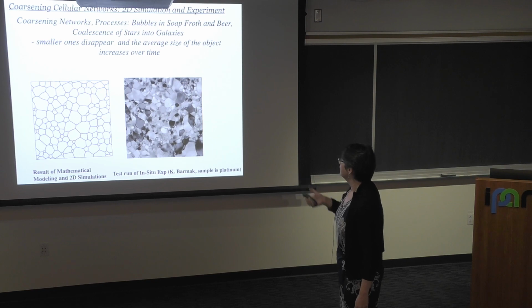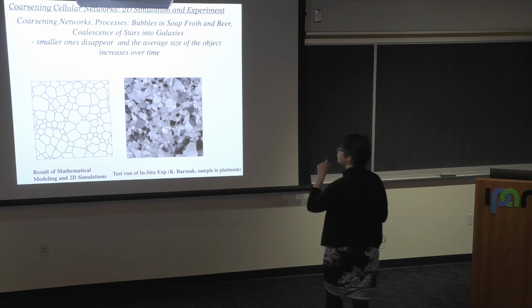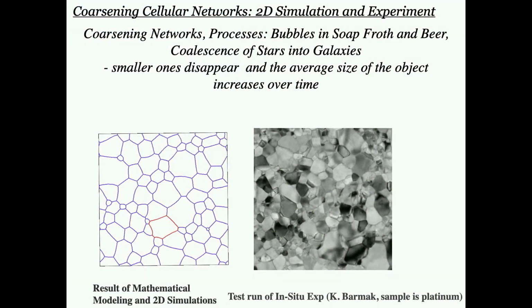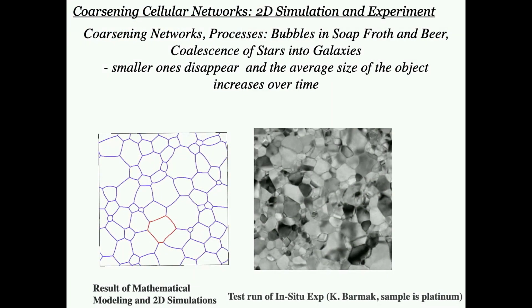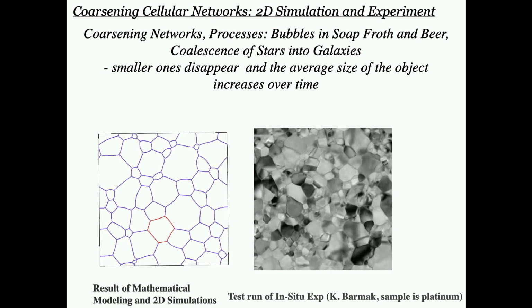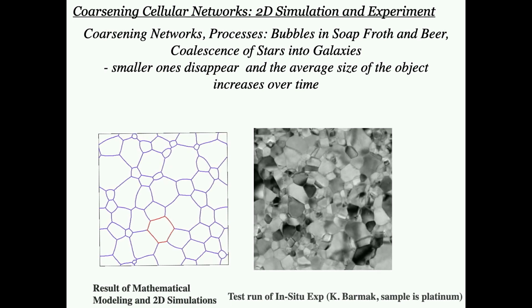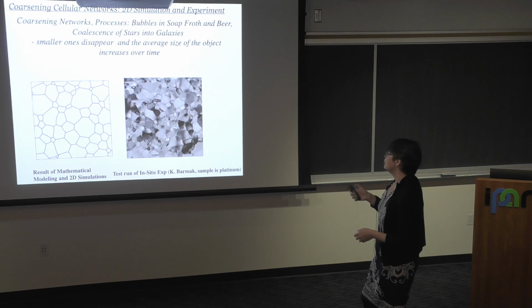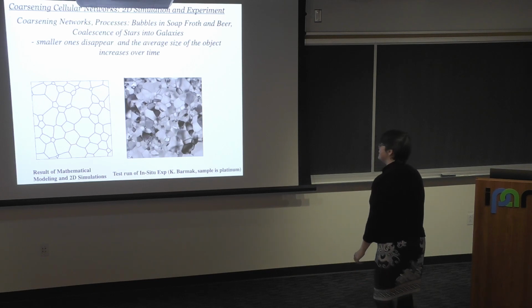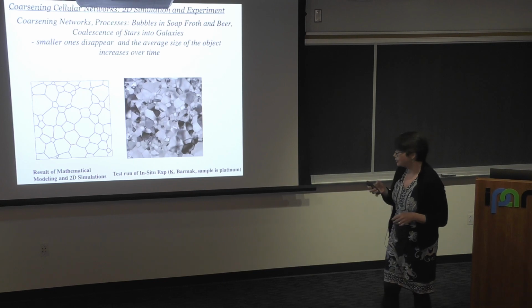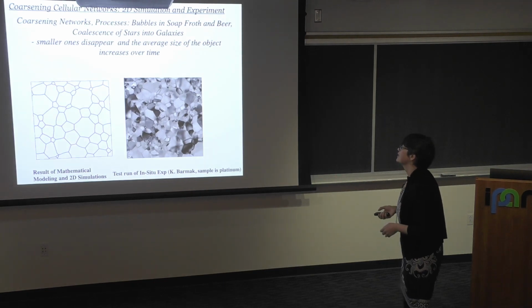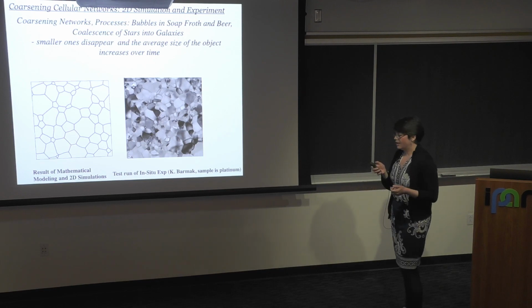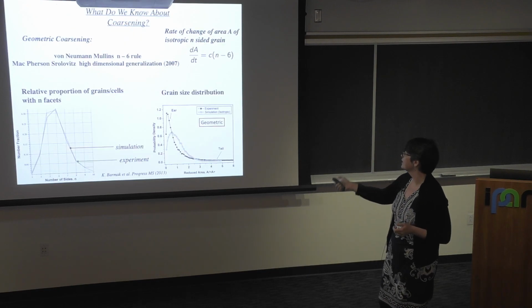And here we have actually very recent in situ experiments. It's a test run of in situ experiments that are quite impressive, and only due to technological progress, only recently was something like that possible, to actually track the time evolution of microstructure in a thin film in real time. And we do hope that we can use in situ experiments to more closely compare our mathematical and computational models and develop more physically accurate models of grain growth.